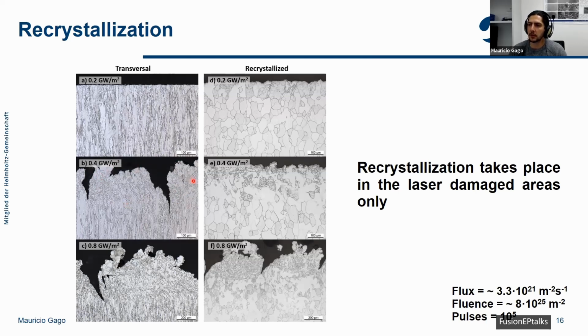So it's merely an effect of the heat loads, and especially the areas affected by the laser at higher power loads, or at 0.4 and 0.8 gigawatts per square meter. The surface temperature increases, and at some point during the temperature peak, the temperature of the samples is higher than the recrystallization temperature of tungsten, which is about 1,300 degrees C.